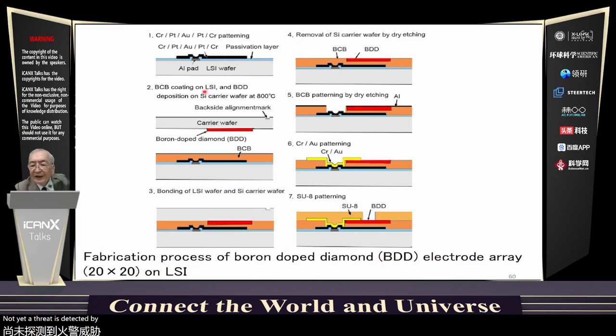The BDD is deposited at 800 degrees centigrade by chemical vapor deposition on the silicon carrier wafer. The flipped carrier wafer is bonded on a LSI wafer by adhesive BCB resin, as shown in 3. After removing the silicon carrier wafer, the BCB is patterned and electrical interconnection between the LSI pad and the BDD is made in 6. Finally, it is coated with the photosensitive polymer SU-8 and the BDD is exposed for the electrode.